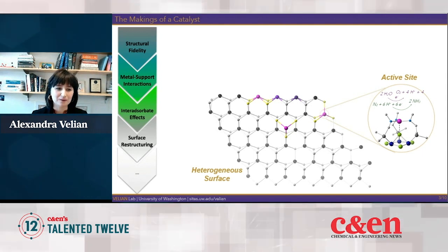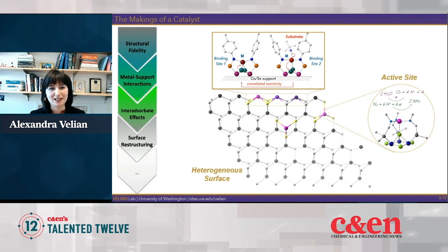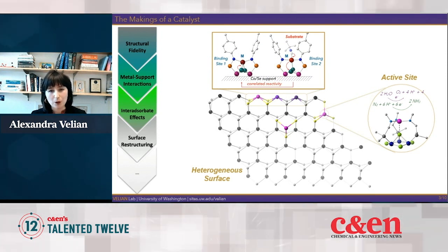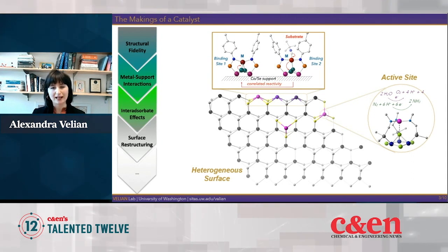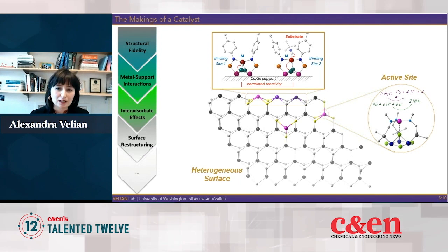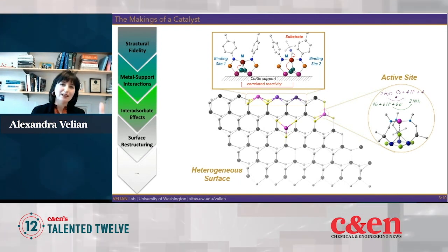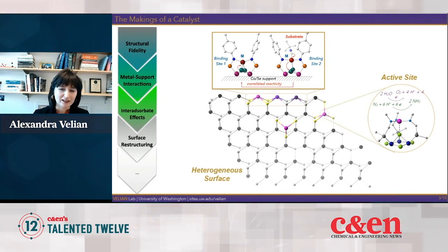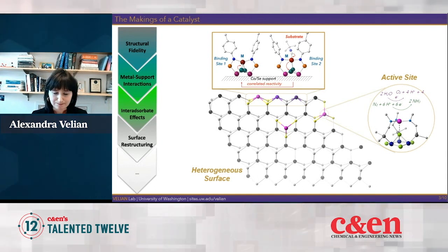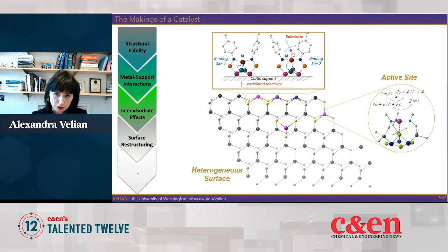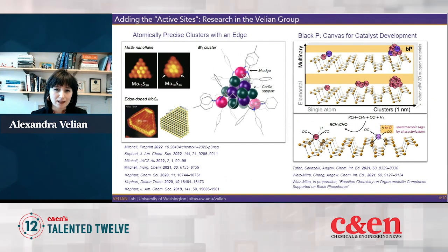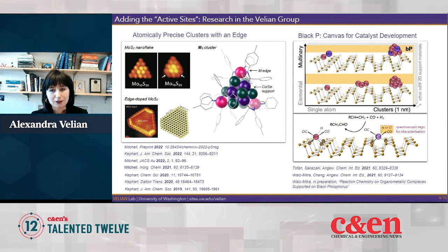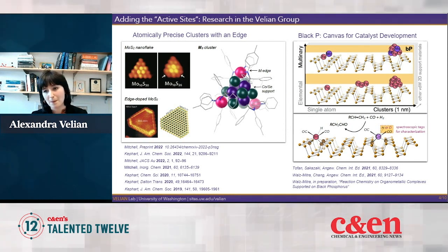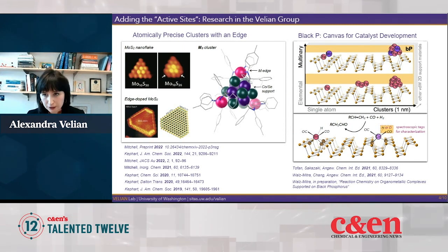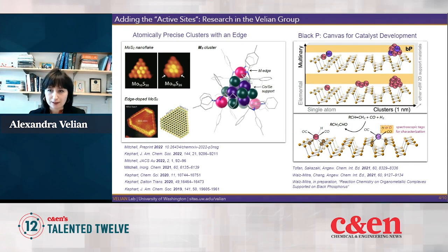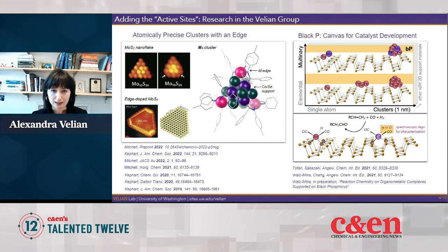And I just want to highlight one such effect that has captured our attention over the past couple of years, and something that emerged from our research, and which is the role of interadsorbate effects in altering activity at chemically identical neighboring sites. So how a binding event at one metal affects that of the neighbor in a catalytic context, and perhaps beyond. So in our group, we take two different approaches to make this vision come to life. On one hand, we anchor atomically defined metals onto a heterogeneous but well-defined surface, the van der Waals surface of black phosphorus, which is on the right side of the screen.